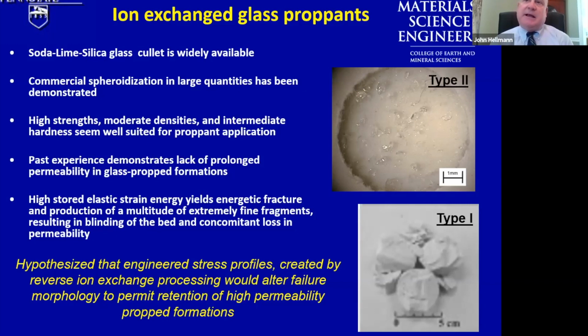What happens to a glass particle when used as a proppant is that when the pressure of the overburden, the closure stresses in the well, is significantly high, on the order of 6,000 psi or so, these beads fail into very, very small particulates. These small particulates are the result of the high stored elastic strain energy at failure. Those small particulates in turn blind the interstices in the remainder of the prop particle bed, and as a result, the permeability of the bed is decreased, thereby decreasing the production rate of the well. So glass is not used as proppants.